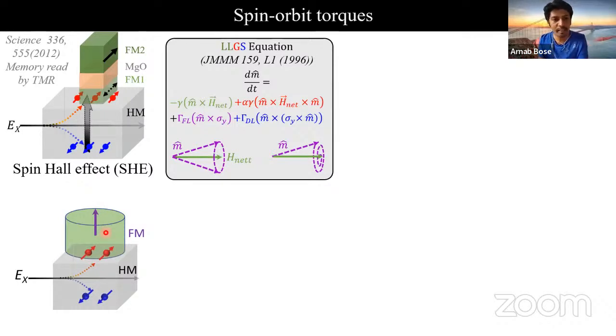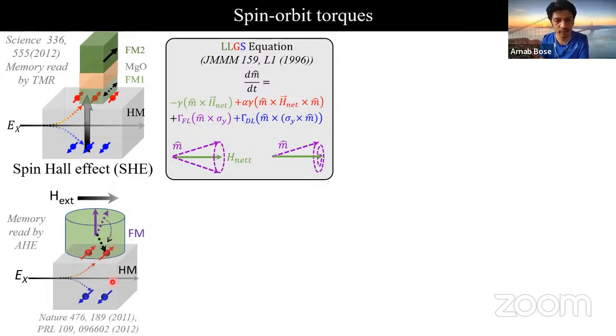But we can always make some tricks, such as by applying an external field, we can tilt the magnetization a bit. And on top of that, spin orbit torque can be activated and it can switch, as reported in these pioneer works. In this case, we can read out the magnetization state by measuring the anomalous Hall voltage. So this is very interesting and quite motivating. This is particularly interesting for the high density memory application.